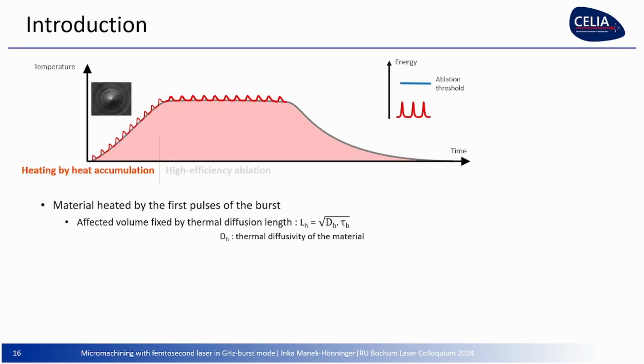There's some volume affected inside. Of course, depending on the material, we have some diffusion length of the heat, which is given by the diffusivity of the material, and of course, the burst duration. So the temporal aspect is very important. We don't ablate, but as one pulse comes after another within the burst, the time is very short, so we're accumulating some heat over a certain range.